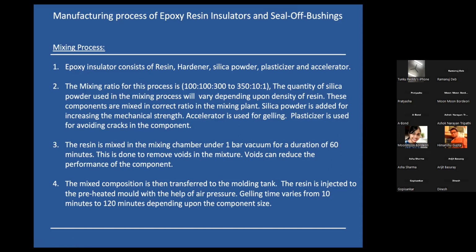These components are mixed in the correct ratio in the mixing plant. The silica powder is used to increase the mechanical strength. The accelerator is mainly used for gelling. The plasticizer is used for avoiding cracks in the component. The ideal pressure at which the composition is mixed is under 1 bar vacuum, and this is mainly done to remove voids in the mixture. Voids can reduce the performance of the component, so it's essential that they are removed during the mixing procedure.